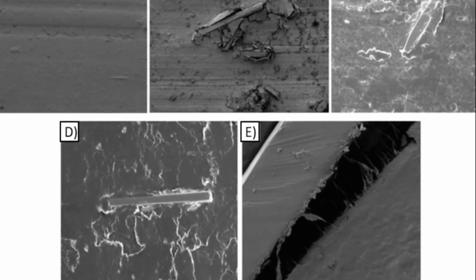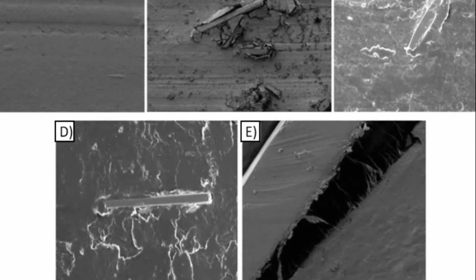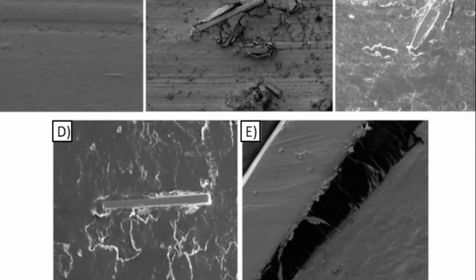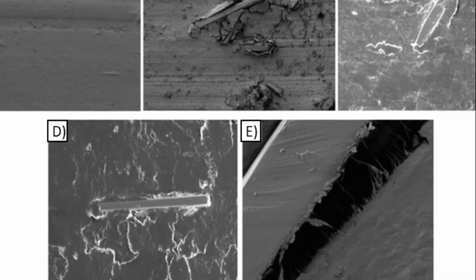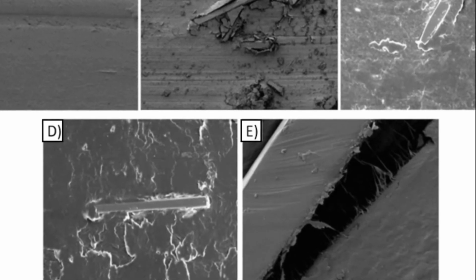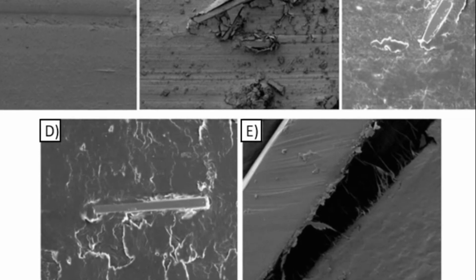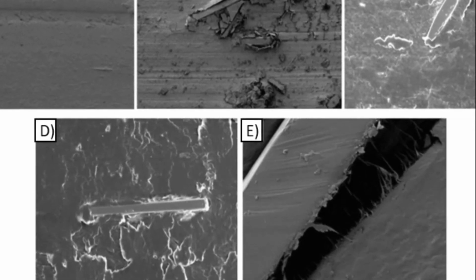In the case of the composite materials with modified fibers, the wear debris were not observed. The friction occurs on a surface of the fibers localized along the friction path due to the improved adhesion interaction between components of the composite material.